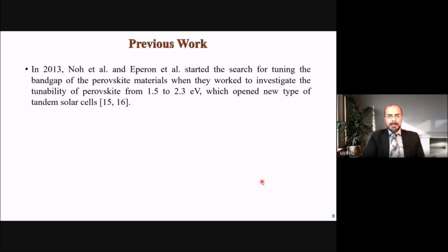So the research has been done since then, 2009, and other groups have done research as well to improve the performance. For example, Noh and his team, and Eperon and his team in 2013, started the search of tuning, changing the band gap for these materials. So they studied these materials, and they did tune the band gap from 1.5 electron volts (eV) up to 2.3 electron volts.